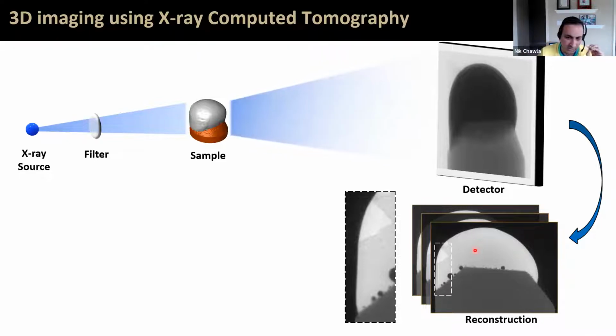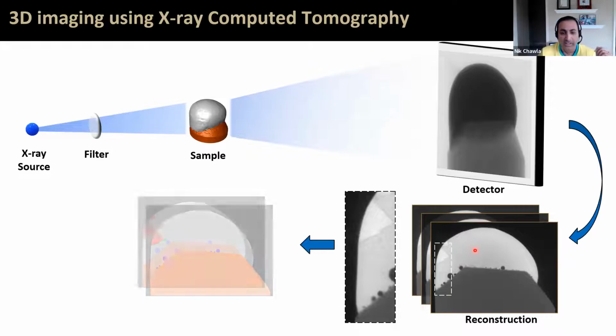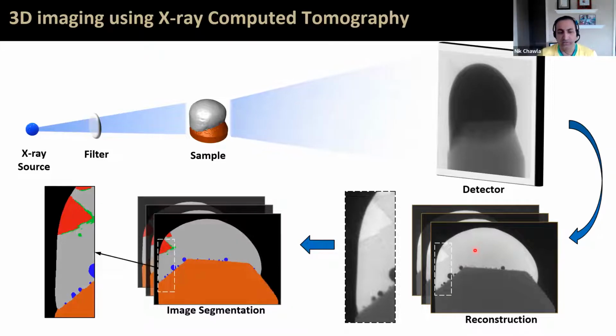But the real bottleneck, the real time-consuming part, and often the most important part, is the quantification of the microstructures. How do we describe the microstructure? How do we get statistics on the microstructure? And how do these particular parameters change over time? And for that, we need to do what's called image segmentation, which can be a very long and laborious process, but it's really very necessary to get statistics on the microstructure.